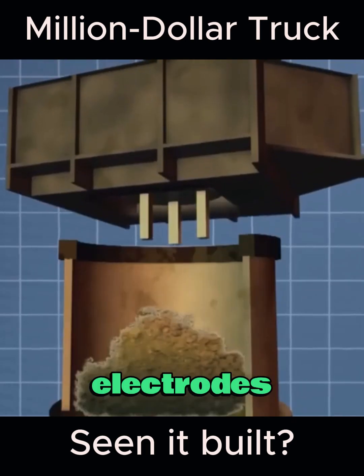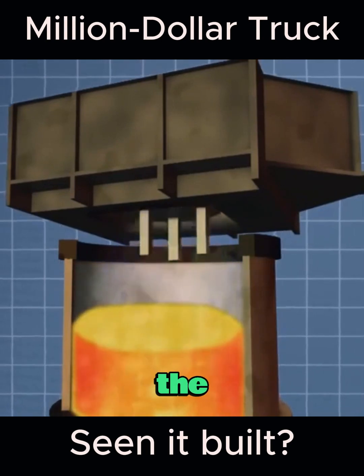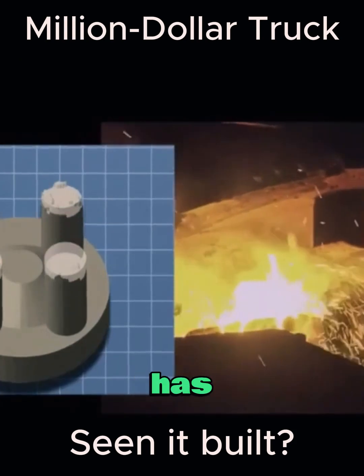Everything is placed into the furnace, and with the use of three electrodes, the 2,200-degree Celsius electric arc melts the metal, taking only 150 minutes to bring the scrap iron to the required 1,650 degrees for casting. As a split casting, the beam has an extremely long cooling time, often taking 36 hours to completely solidify and turn into solid iron blocks.